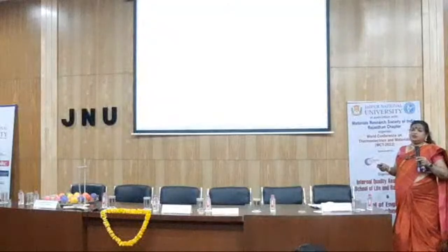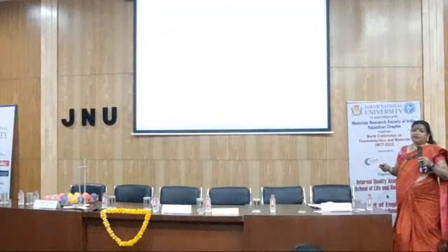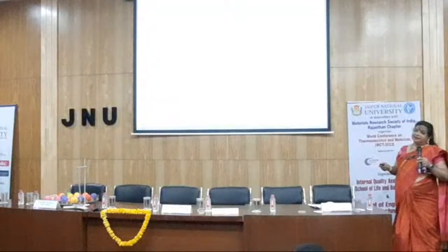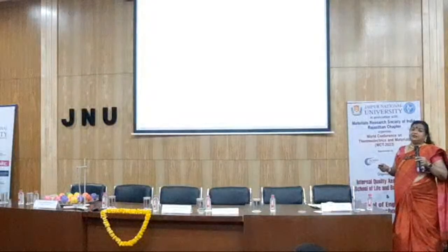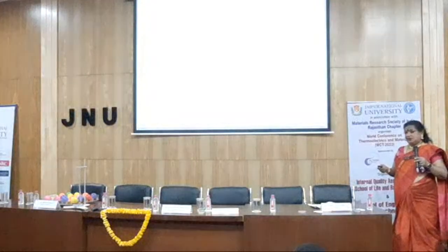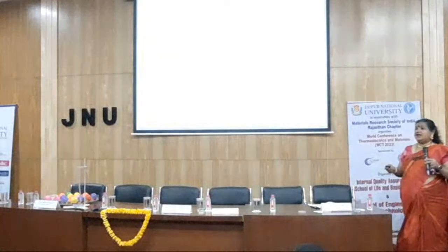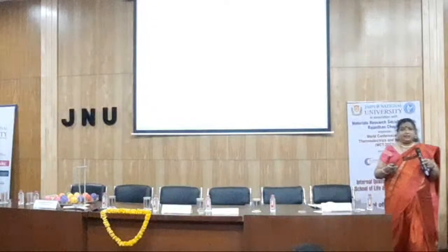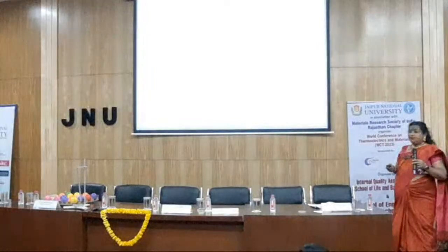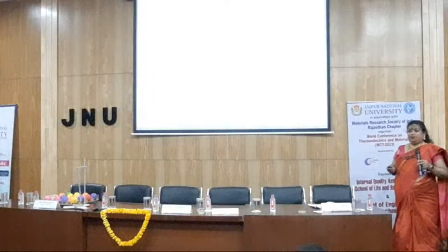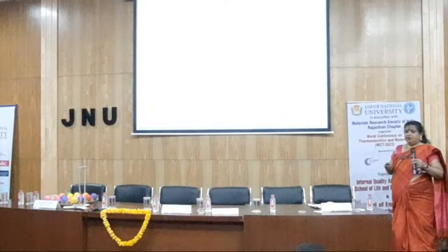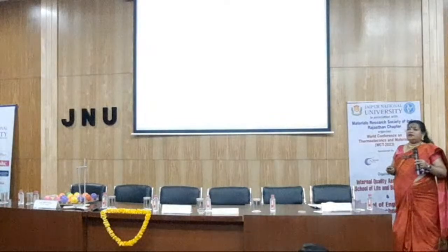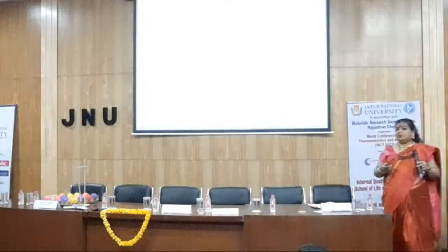Gemstones, we cannot break them. Okay. And I found out by XRF that the synthetic ones are different from the natural ones. And the main thing is natural has Fe in a large amount, and synthetic doesn't have it. Second thing, I did by PIXE also, and I got very beautiful spectra with the PIXE. And again, I talked about the ink sample.